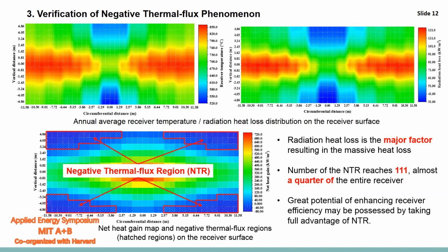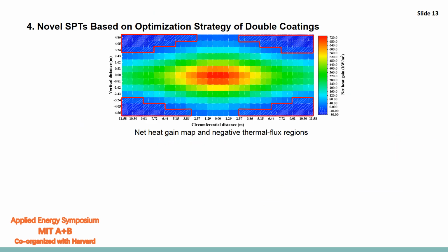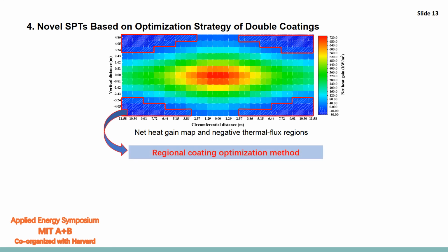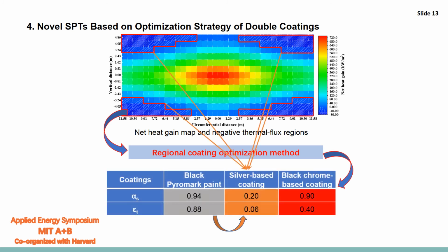In this context, we are thinking about how to take full advantage of the NTRs to enhance the receiver efficiency. We proposed the regional coating optimization method. We changed the original black Pyromark paint into other coatings with lower emittance. In this study, we selected silver-based coating and black chrome-based coating. We can see in the table that the emittances of the silver-based coating and black chrome-based coating are only 0.06 and 0.4, but the solar absorbances are reduced to 0.2 and 0.9.